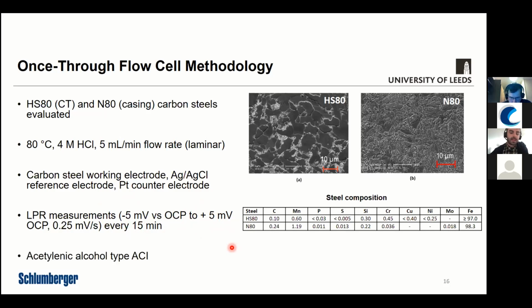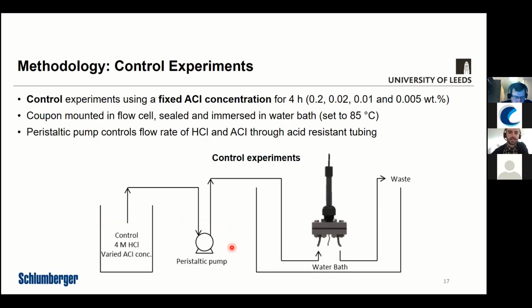And we used a polymerizable inhibitor, one of Schlumberger's inhibitors, to evaluate how effective this inhibition technique was using our flow cell. So there's 2 types of experiment that we completed. So we have a control experiment, which is where we have a fixed inhibitor concentration. So this isn't a staged approach experiment. It would just be a consistent inhibitor concentration for 4 hours. And these are the 4 concentrations that we used.